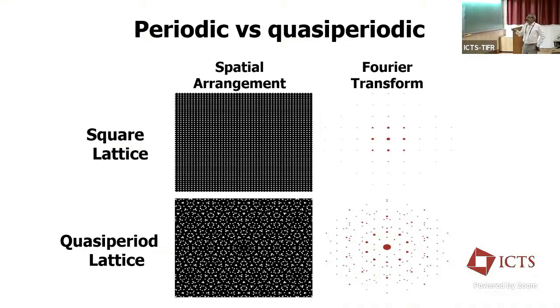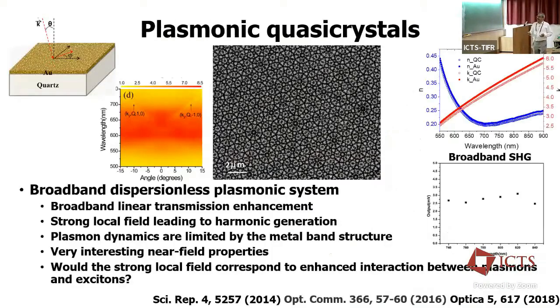However, with the same density of scattering elements in a 5-fold rotation quasi-periodic lattice, the K-space is very dense. You have different magnitudes of Ks, so you have a broad wavelength response. You have no polarization dependence and no launch angle dependence in this case. That's what we showed here. So this band will have dispersionless plasmon modes within it. We showed that we can now launch plasmons by just shining light on this kind of structure, where you have this top air-gold interface and gold substrate interface. You can have two surface modes depending on the thickness.